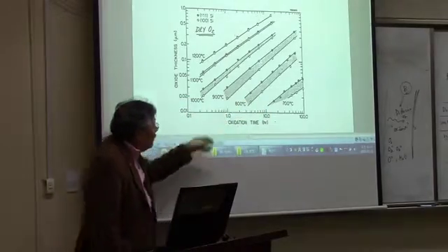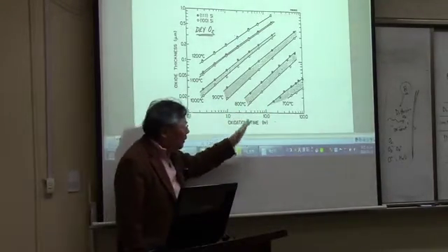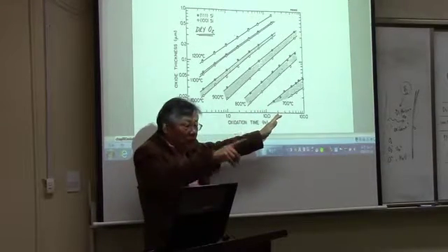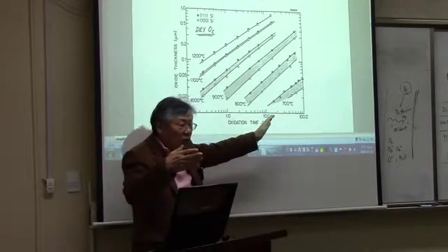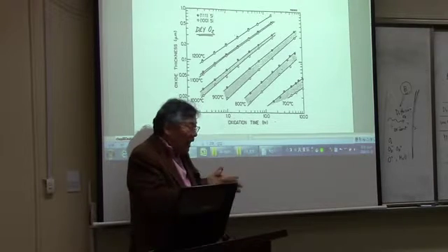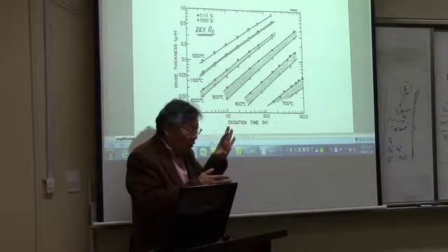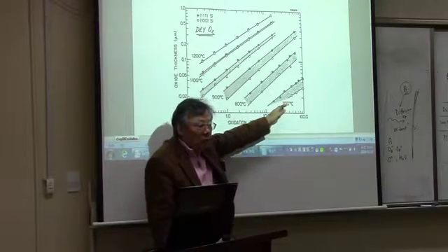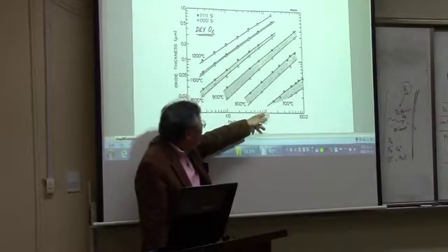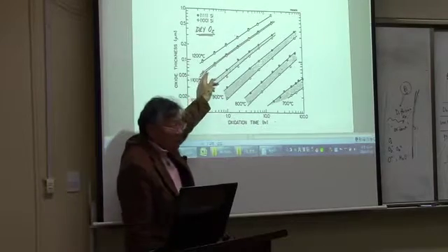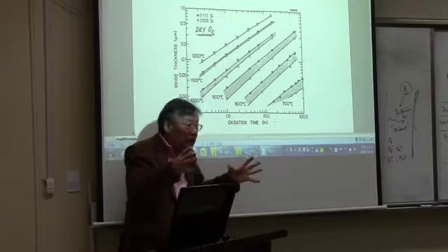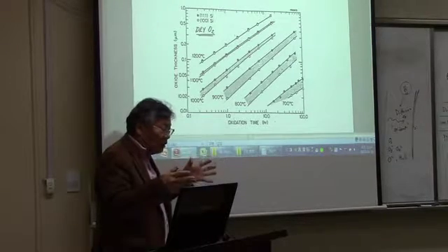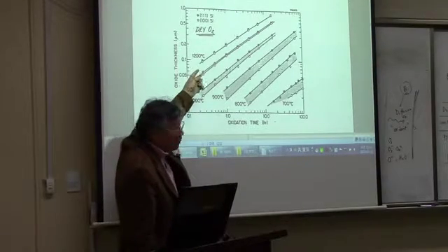This means at the low temperature, the surface reaction flux F3, which is related to the reaction at the interface between oxide and silicon, is more important. And as you go to high temperature, then the diffusion of the oxidant in the oxide is more important, so that